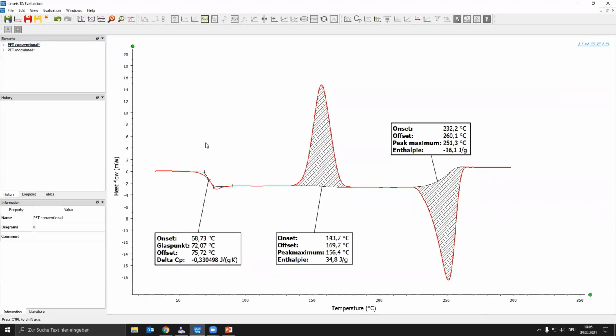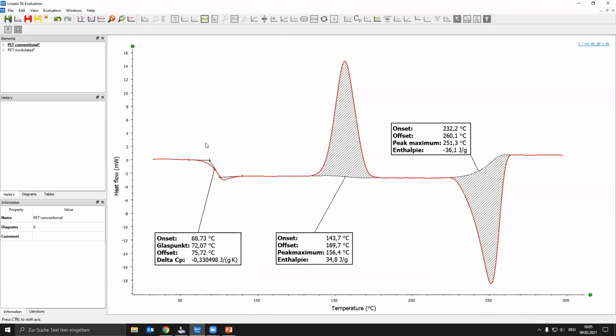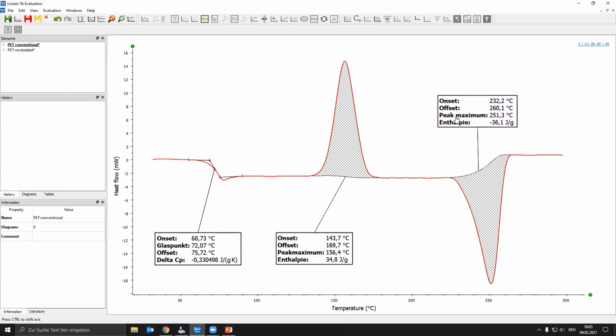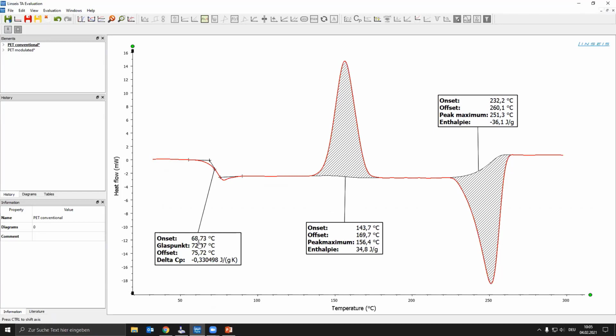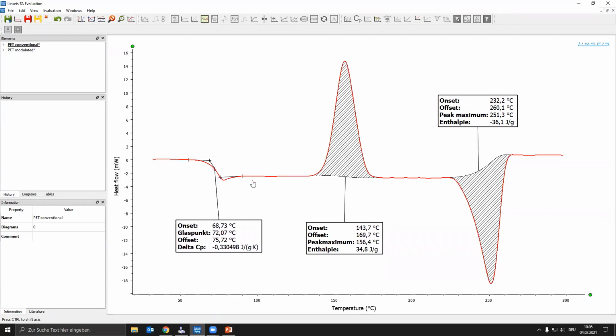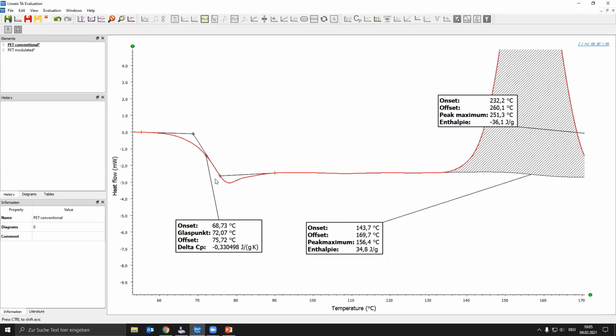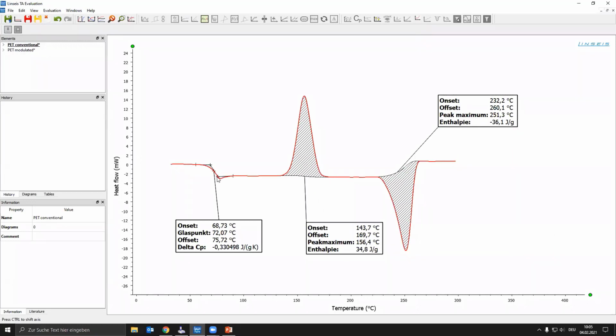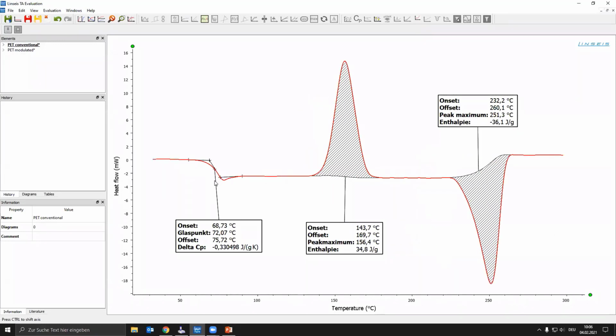Now, let's talk about the results. At first, here we can see the PET measurement with conventional DSC. So, as I already explained, at first we can see here for this sample the Tg. And what we can also see here is the relaxation peak. So especially to evaluate your Tg with intersection, the hysteresis peak or the relaxation peak will affect the result for your glass transition. So here, again, one of the advantages of the temperature modulation: we can split it into reversing and non-reversing parts. Next, of course, we can see here the recrystallization peak and the melting peak with the line due to the lower cp values.